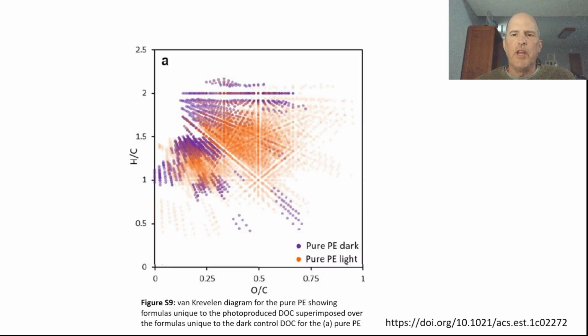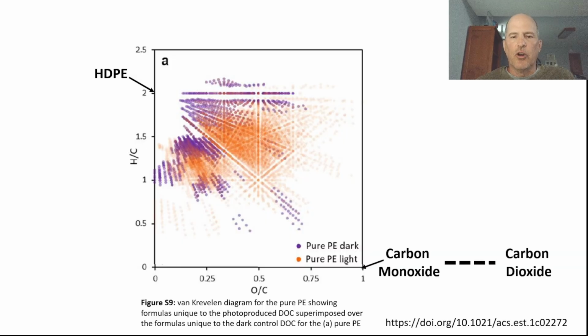This is a kind of a cool way to represent the distribution of products. So here, instead of molecular weight, they're looking at it in terms of atom ratios. So the x-axis is the ratio of oxygen to carbon. The y-axis is the ratio of hydrogen to carbon. And you can see, again, where you would start would be in the upper left in this case. That's where polyethylene would be, a hydrogen to carbon ratio of very close to 2. And then carbon monoxide would be at the bottom right, and carbon dioxide would be a little further even to the right. So again, you can kind of see this progression from plastic to gas. It goes through a gazillion different intermediates that have different amounts of oxygen to carbon and hydrogen to carbon ratios.